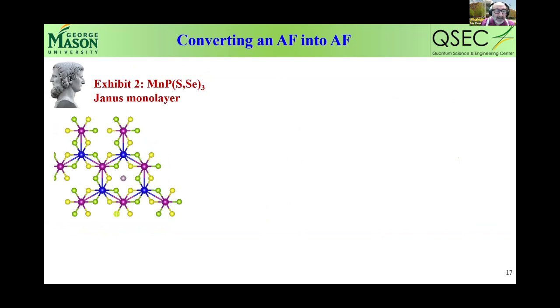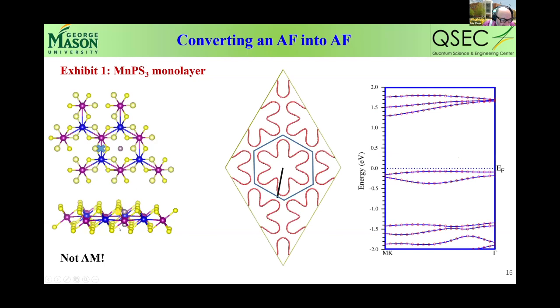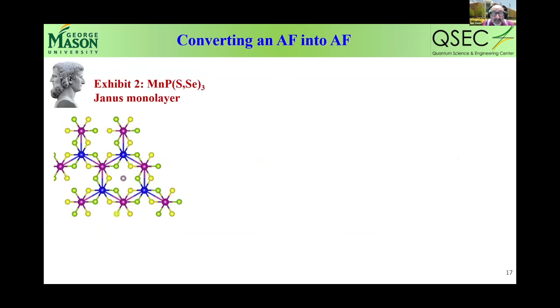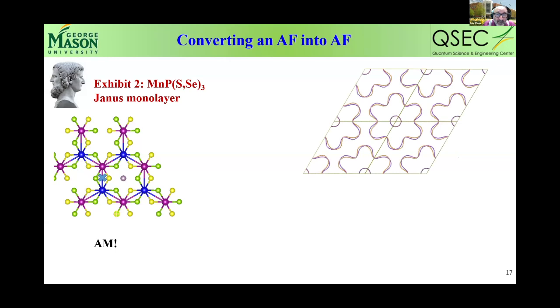So now I will give you three ways in which we can slightly modify this material and make it immediately altermagnetic. In this case, I make it Janus. The Janus means that my bottom layer, you remember I was showing that this is a bottom layer and top layer. Now, this material exists in this mixed phase as well, but so far experimentally, the selenium and sulfur are always distributed uniformly. In principle, for other chalcogenides, people can make a Janus monolayer, which means that the chalcogen below the manganese layer is predominantly sulfur and above predominantly selenium. Then this point is not an inversion symmetry anymore. There is still a mirror symmetry which converts them. So it's, of course, fully compensated by symmetry, but now it becomes altermagnetic.